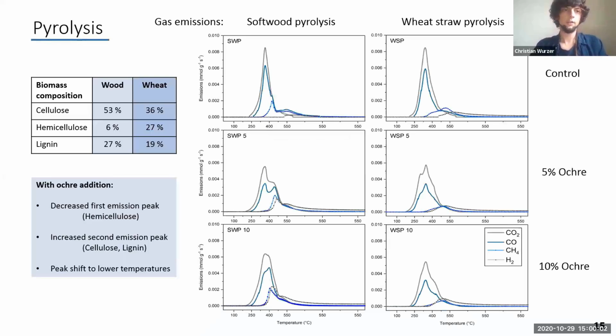At first we looked at the pyrolysis process. On the top left, you can see the lignocellulosic composition of the 2 feedstocks. The main difference is that wood has a higher cellulose and lignin content, while wheat straw has a higher hemicellulose content and also a higher ash content, which is not shown here. On the left of these 2 columns, there's softwood pyrolysis with the top no ochre addition, the middle one with 5% ochre, so 2.5% iron, and the bottom one with 10% ochre addition.